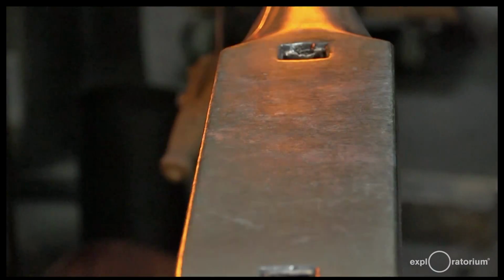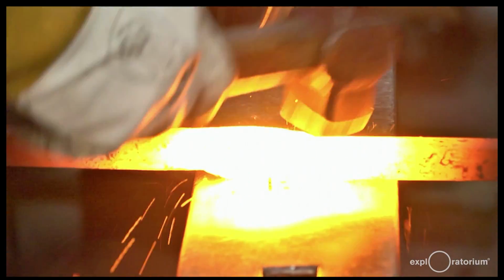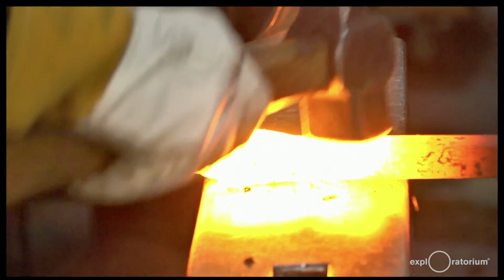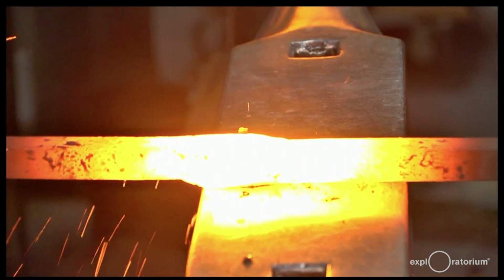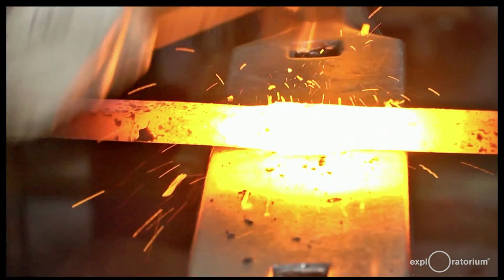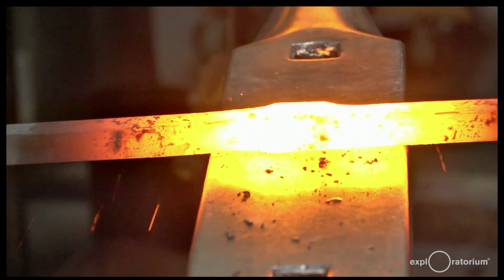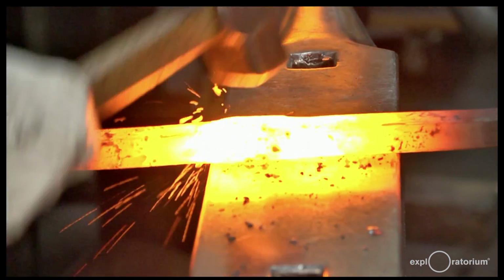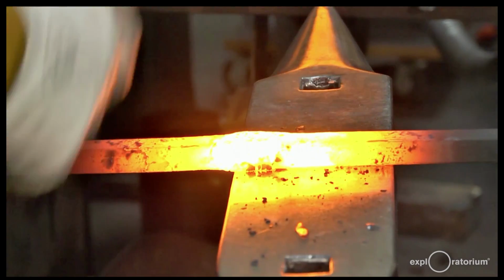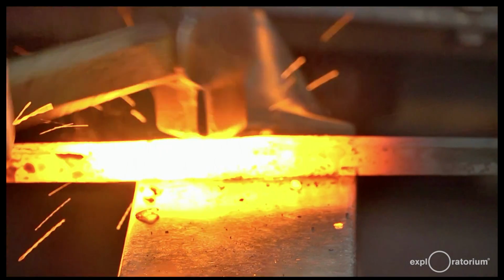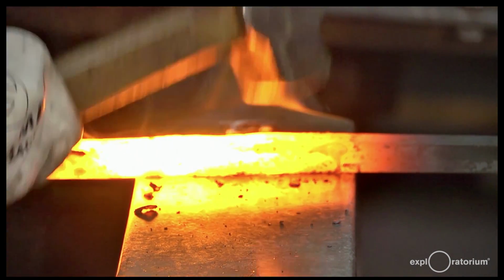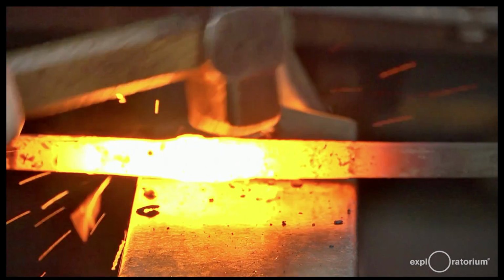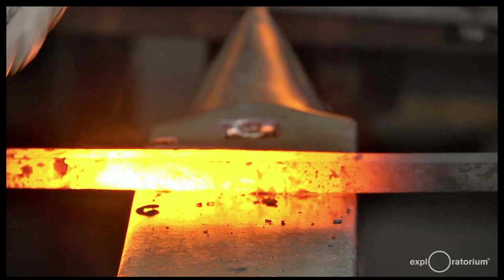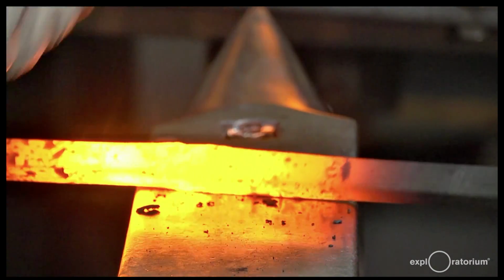The weld is essentially done now, but the piece is very irregular, so the work after this is all geared towards getting the bar back to a nice straight square shape. And the flakes that you see coming off laying on the anvil are iron oxide. In industry where they produce tons of that stuff, they actually collect it and put it back to smelting because it's essentially pure iron ore.